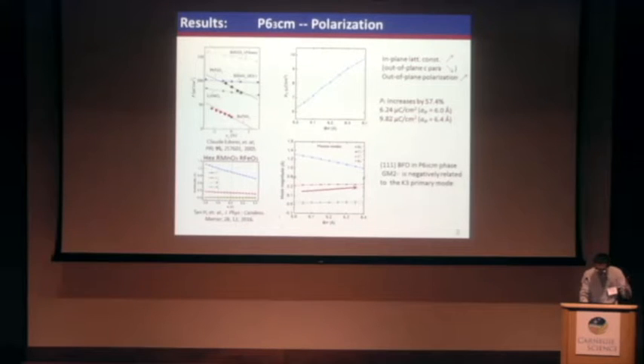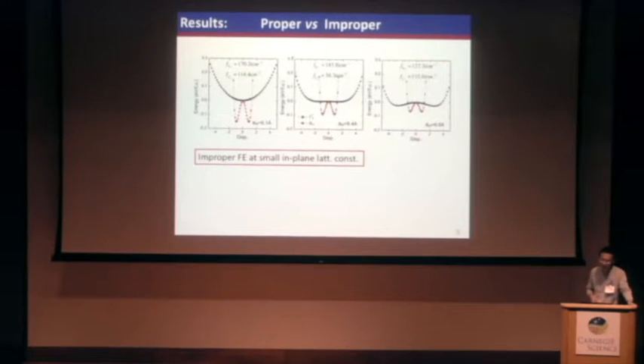So what's behind that? Let's look at the energy landscape of the K3 and gamma-2 minus mode. At small in-plane lattice constant, the K3 has a double well. Means that this is the primary phonon mode, which is also the driving force of this phase transition. While the polar mode is a single well. That means the polar mode is induced by the K3 mode.